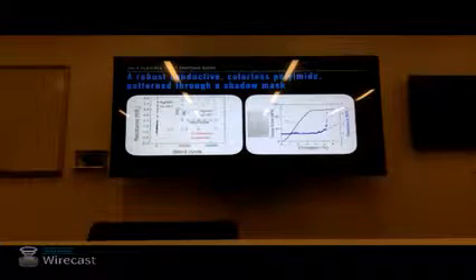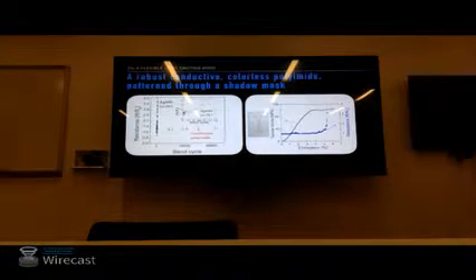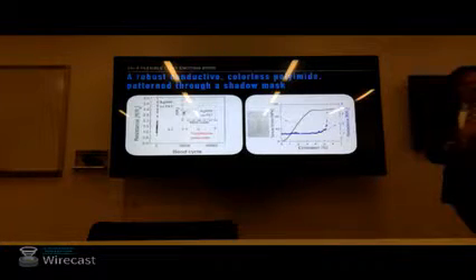Yeah, Barry. Is the failure there due to the polyimide or the silver nanowire? The silver nanowires fail first, then the polyimide. But if you think of it as a composite material, you could say that the strain at which conduction goes away is lower than the strain at which this thing breaks in half.